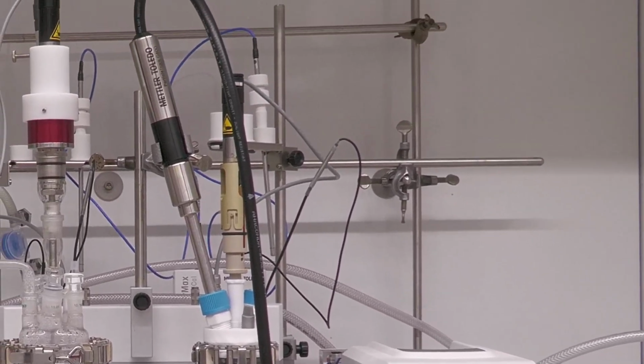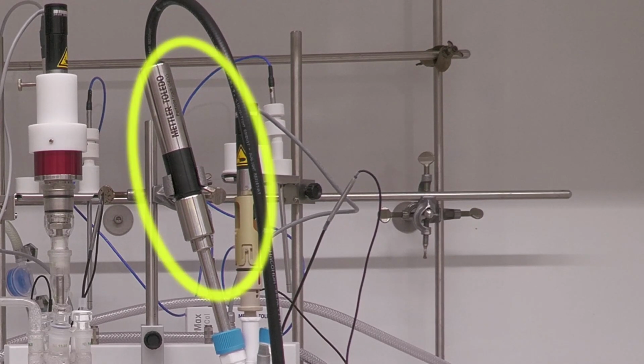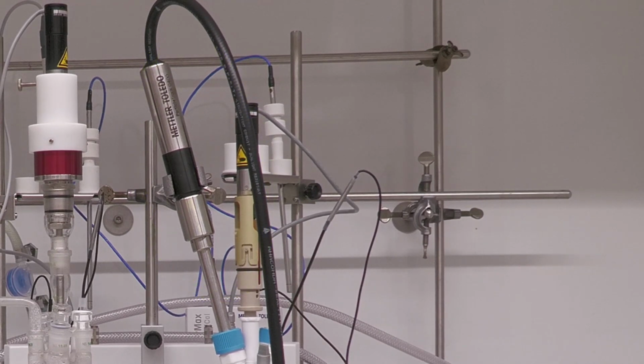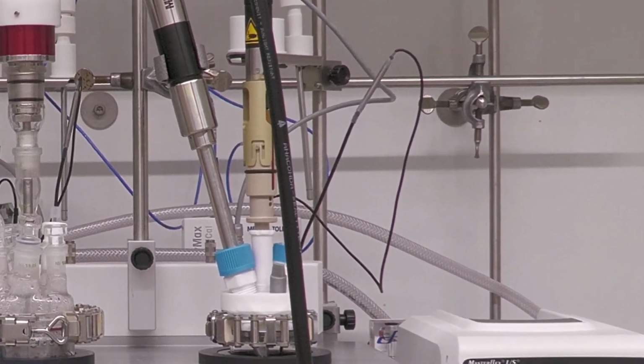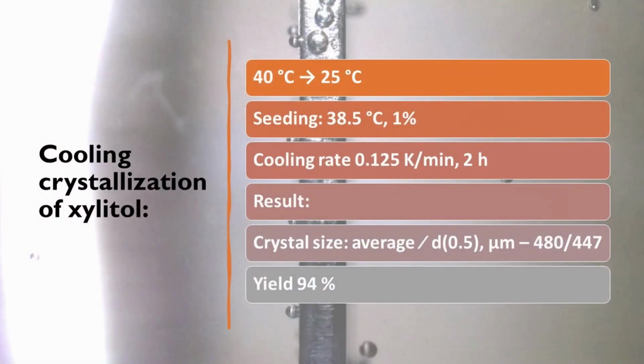Focused beam reflectance measurement is used in our crystallization studies because it allows us to obtain some kinetic data corresponding to nucleation and crystal growth rate. A highly precise chord length distribution sensitive to particle size and count is reported in real time. Next, let's take a look inside the reactor to see what is happening there.